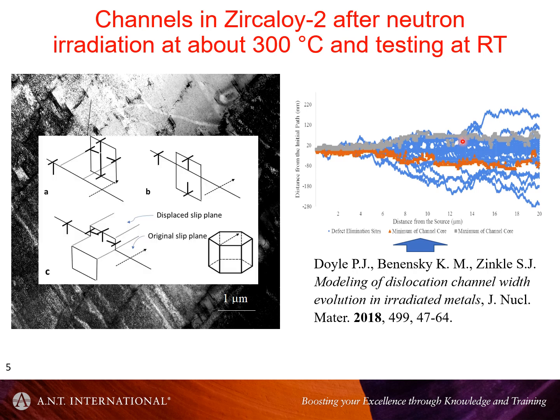So what are we talking about? Basically, a dislocation will be moving through a crystal. It'll come up against a prismatic loop. It'll incorporate the loop. This is a very simple scenario here, and carry on. In doing so, this portion of the dislocation has climbed compared to this. The dislocation being an edge dislocation in this case, it only works for edge dislocations, although I think there can be some helical climb interactions, but I'm not sure how that necessarily sweeps up the loops for screw dislocations. Perhaps the screw dislocations allow the loop to move out of the channel easier. I don't know. The observation is that you get this clearing.